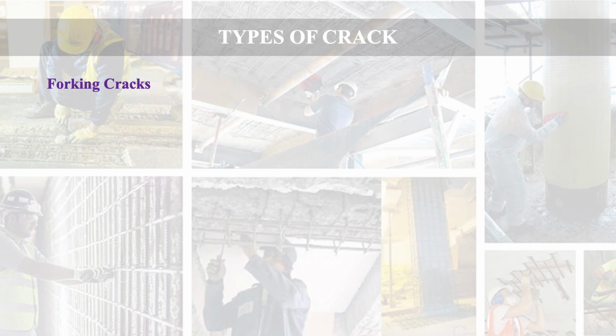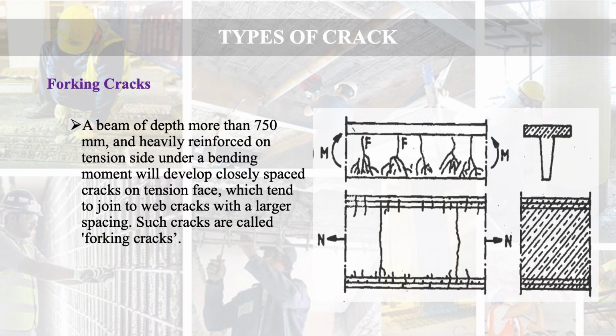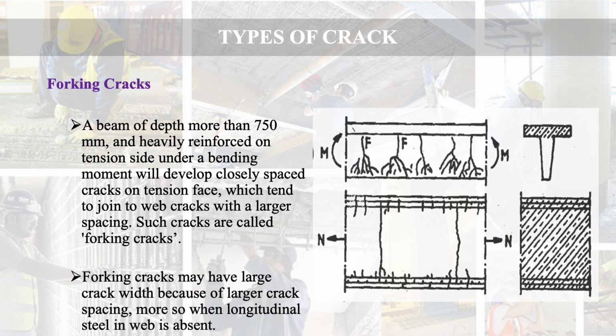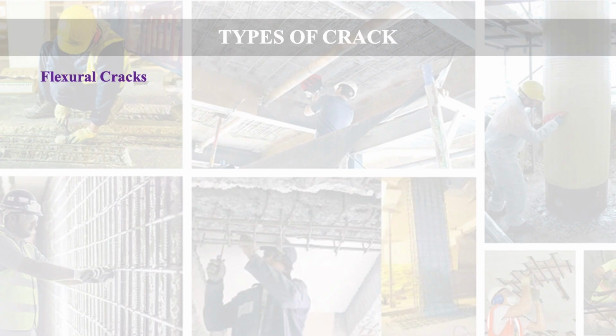Next are forking cracks. A beam of depth more than 750 mm and heavily reinforced on the tension side under a bending moment will develop closely spaced cracks on the tension face, which tend to join to web cracks with a larger spacing. Such cracks are called forking cracks. Forking cracks may have large crack width because of larger crack spacing, more so when longitudinal steel in the web is absent.